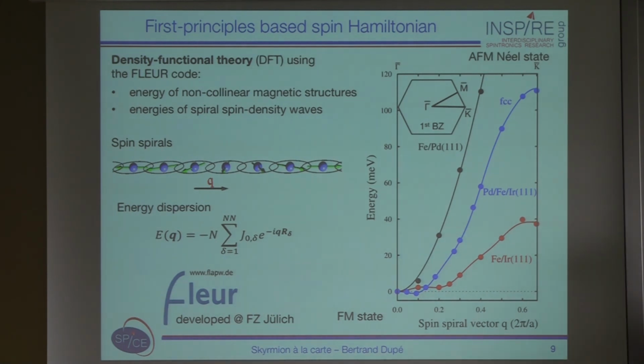of the dispersion curve. So here you can say that this is actually showing that the ground state of the system is a non-collinear magnetic structure that we call a spin spiral, and this Q vector, the propagation vector Q, can actually be read here. So it has a period of 7 nanometers, just coming from exchange interaction. So in order to model this kind of curve, you need to have interaction beyond first nearest neighbor.